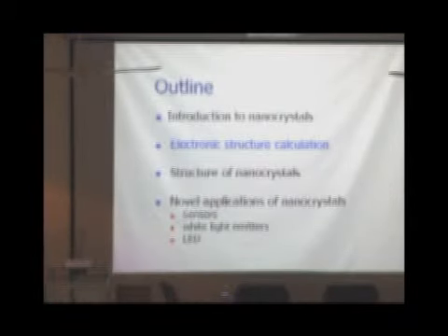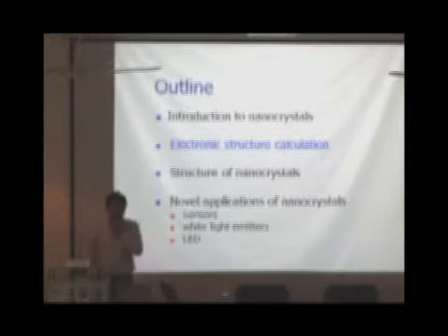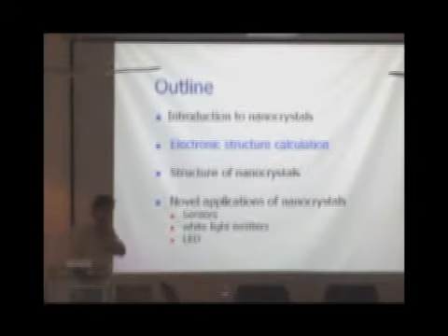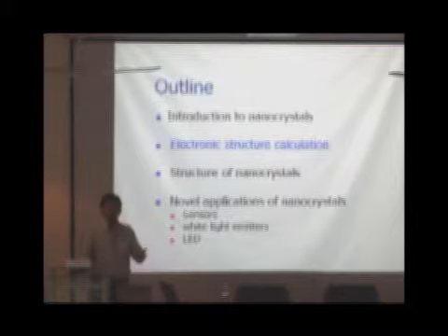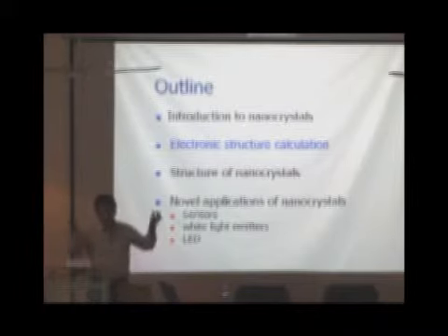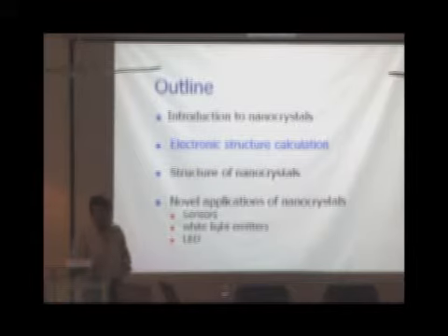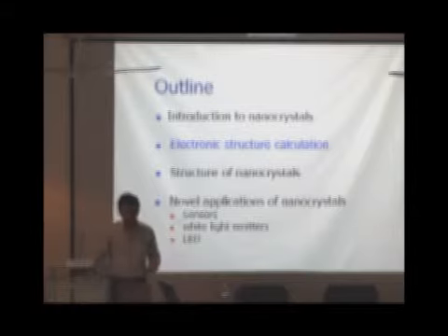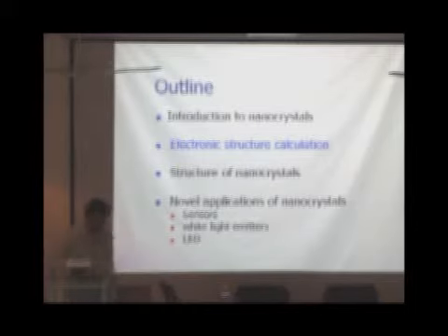So much for the introduction to the world of semiconductor nanocrystals. I'll move on to electronic structure calculations. I just mentioned briefly that you can use, for example, the particle in a box model for a spherical particle with infinite walls, and if you use an effective mass instead of the free electron mass, it is known as the effective mass approximation, proposed as early as 1982 by Louis Brus, who is considered one of the fathers of nanoscience.